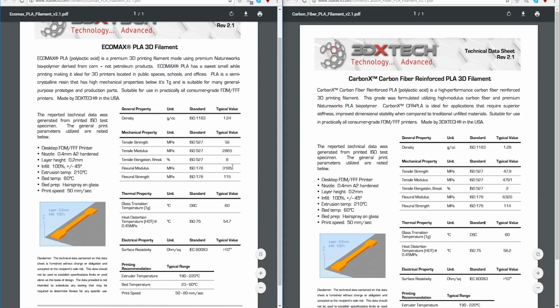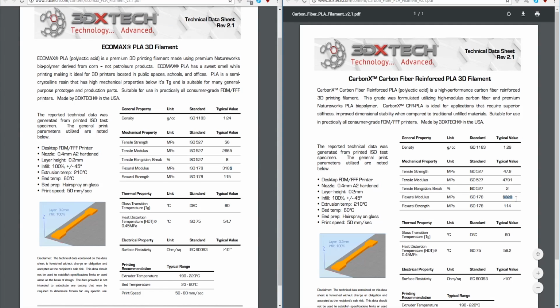Again, flexural modulus, you'll actually see here in the flexural modulus that it is drastically better in flex. So if you have a part that you're using carbon fiber, when you design it, have it in bending instead of in pulling, right? Have it in a flex instead of pulling, and you drastically increase your modulus there. So this one's just as good in tensile as it is in flex. So overall balanced material. This one has drastically more flex stiffness than tensile stiffness.